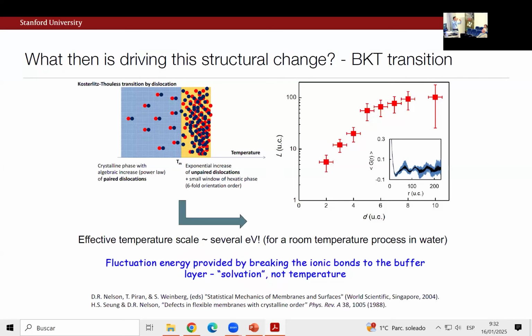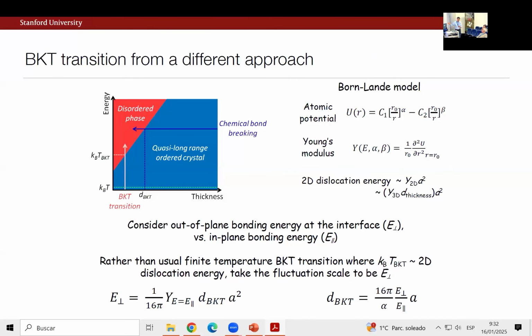It sounds gentle, but when you dissolve your salt crystal or something like this, you're really breaking an ionic bond. This is the scale of that bond. So our idea was that as gentle as this may seem, by dissolving this layer out, perhaps what we're doing is taking a trajectory related to the so-called BKT transition. The real transition is a discussion in terms of raising temperature and crossing over the proliferation of topological defects. But imagine that as a function of thickness, we're really coming across this at a high energy scale.